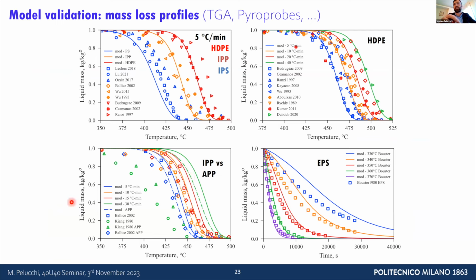What I'm showing here is the first level of validation of these semi-detailed chemistry models, where we look at the mass loss profiles from TGA measurements. So we're looking at a very small sample, milligram, pulverized sample of polymer, so no heat and mass transfer limitation. And we basically look at the chemical kinetics of degradation.